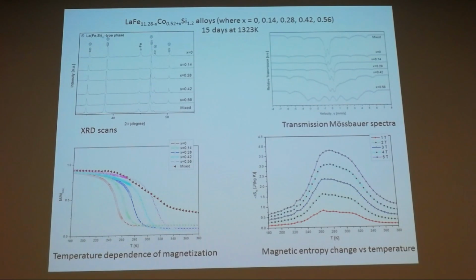into pellets, and measured the Mössbauer spectra, X-ray diffraction, and also some magnetic measurements. And we have shown that the magnetic entropy change takes a table-like shape with temperature. One has to remember that for room temperature applications, magnetocaloric materials have to work not at a single temperature, but in a range of temperature. Therefore, it's just an example of how it is possible to gain that.